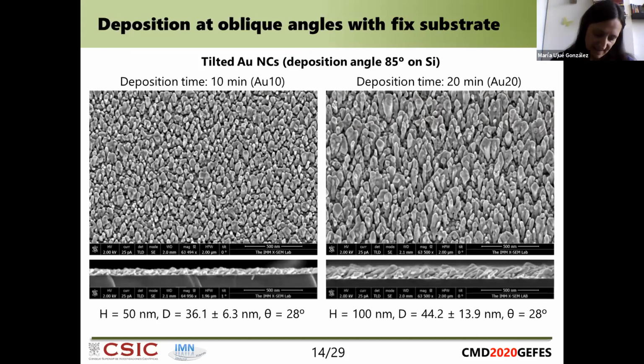One of the most analyzed properties of the plasmons, and one of the most desired ones, is surface enhanced Raman scattering, because it's very useful for sensing. So we thought that maybe with the nanocolumns we could also get some interesting behavior in terms of that. But in this case, of course, we were not looking for that black gold, we were looking for bright gold. And so we did it without rotating the substrate. In this case, we used the high angle, but the substrates were fixed in such a way that we were obtaining well-defined and tilted columns, tilted with regard to the substrate.